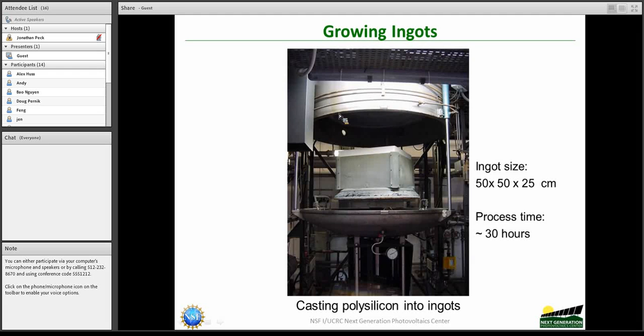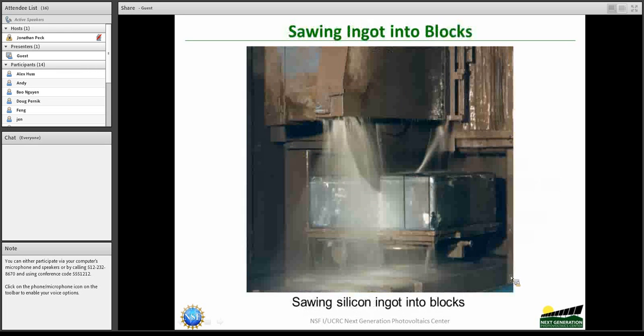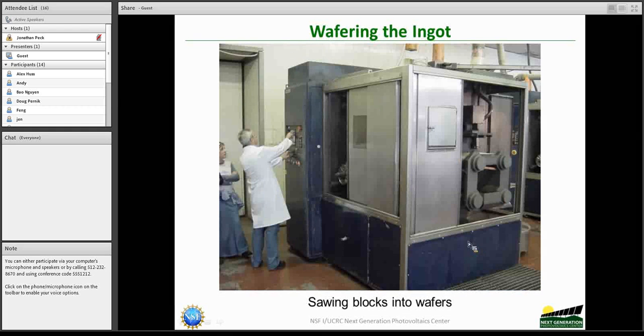So this is a fairly large vacuum furnace into which you load the silicon material, and you pull a vacuum, melt it, and cool it slowly. And typically the process time from the starting feedstock material to an ingot is roughly in the neighborhood of 30 hours or so. The next step involves sawing the ingot into manageable blocks, and here you're looking at a diamond saw that takes that ingot and slices it into blocks. And the next step is to slice the block into wafers. This is usually done by a wire saw with abrasive slurry. And nearly about 50% of this pure material is actually lost during the sawing process on average. And that's a fairly significant waste. And this is the sawing of the block into wafers.